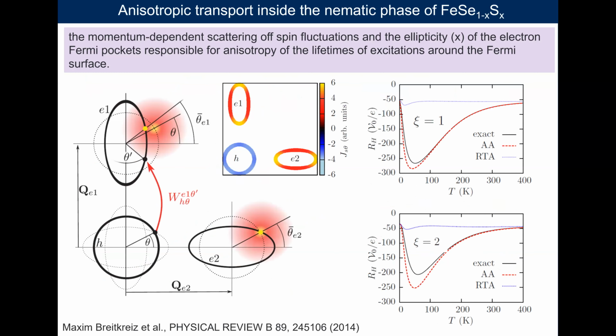A possible explanation proposed in this paper is that when we have strongly momentum-dependent spin fluctuation and strongly elongated Fermi surfaces, then we might expect strong anisotropy in the lifetime of excitation in the Fermi surface. And here they model the behavior of the Hall coefficient as a function of temperature as one increases the ellipticity. So the more elongated the pockets become, the stronger the effect in the Hall coefficient is.